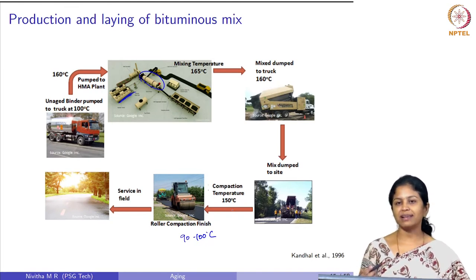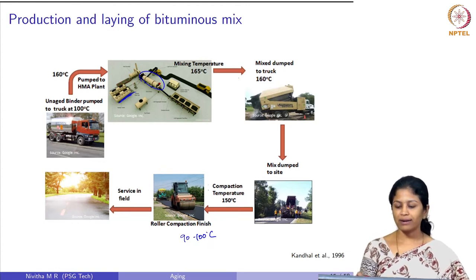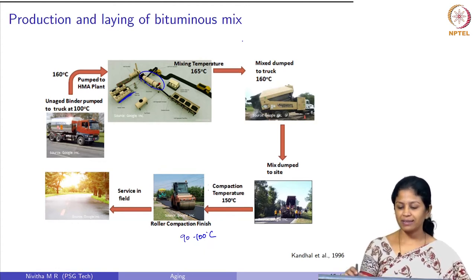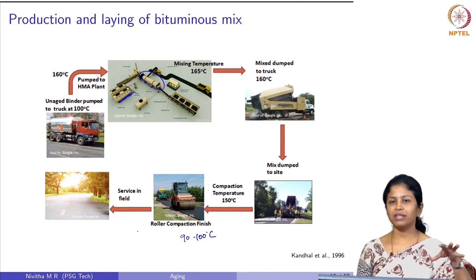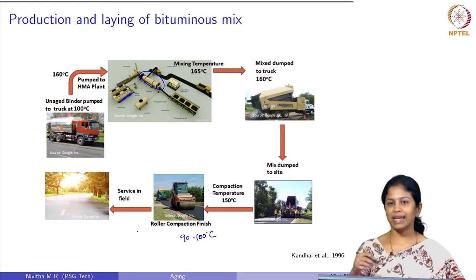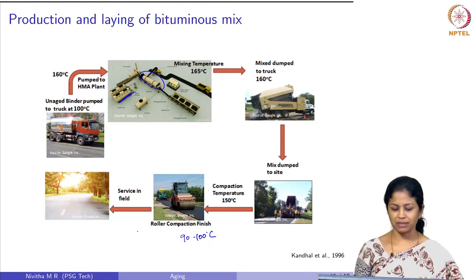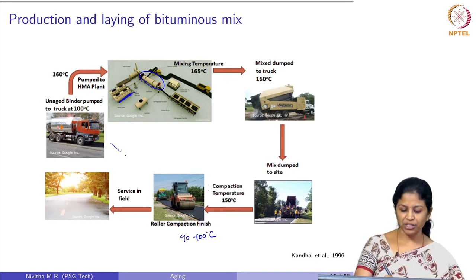We said temperature acts as a catalyst. The temperatures range from 100 to 165 degrees Celsius throughout this entire process. After the mix is subjected to environmental conditions, the temperatures are different — pavement temperatures show cyclic variation on a daily basis and on an annual basis. This process, from when bitumen leaves the refinery to the end of compaction, is called short-term aging.